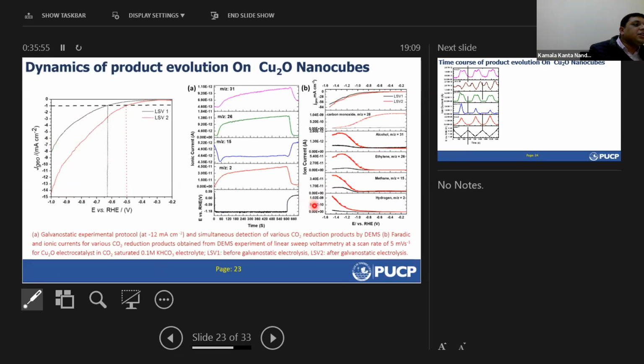For example, here if you can see, when we applied 10 milliampere per centimeter square, we obtained a bias of minus 1.2 volt. Hydrogen production started instantly. But if you see the CO2 reduction, it started with a delay. That means the catalyst is taking 30 or 40 seconds under applied potential to reorganize itself for CO2 reduction. Again, when you see the increase of the currents, it increases up to 110, 120 seconds, and it gets stabilized in the case of ethylene, but for ethanol, it grows continuously. Okay, that means the ethanol production is increasing with time, whereas the ethylene formation gets saturated after some time from the start of the electrolysis.